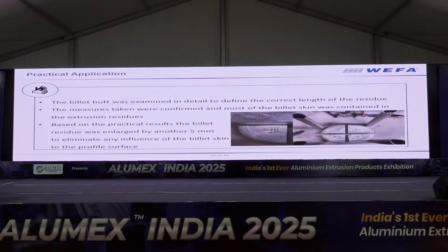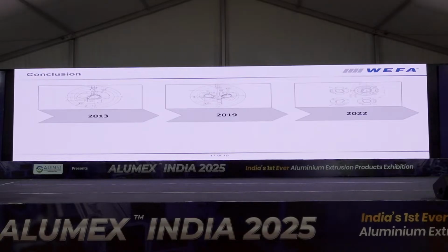What we also did in the end, we recommended the extruder to increase their butt length a little bit by only 5 millimeter. You see 5 millimeter is not much, but it helps tremendously to reduce the billet skin inlet. That's always something we recommend, not to save on extrusion and better have a longer billet butt in the end to also create a better surface quality in the profile. So that was the overall success story. To conclude, finally, we found the cause of the surface defect and could increase the productivity.